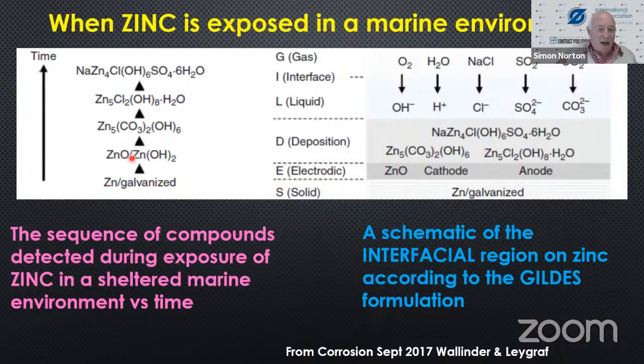Initially, zinc oxide and zinc hydroxide form instantly, even before exposure to a marine environment, because of the oxygen in the atmosphere. Then the next compound that forms, because you've got carbon dioxide in the atmosphere, is this material here, which is called hydrozincite. This material then subsequently forms because you've got chlorides in the sea spray. This is actually called Simonkolleite as a mineral name. And finally, this material over here.